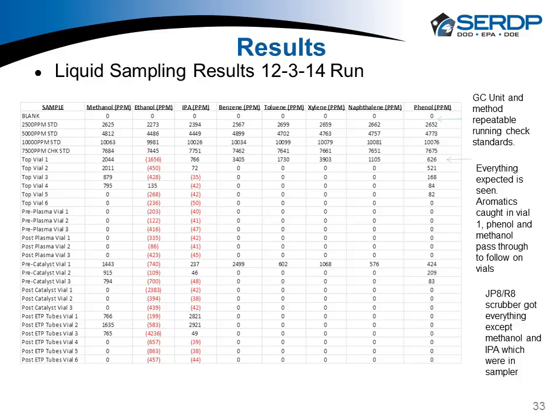December, a little bit better results in terms of seeing all the chemistry that we thought we would see. Another key point I wanted to make is, we were running the 6 vials. Usually we just analyzed 3 of them because everything was getting captured for the most part in the first vial of the liquid. The only thing that really transferred down through was the methanol and the phenol, which is interesting and kind of unfortunate because that's a toxic material that we would not want to have escaping to the environment any more than possible.